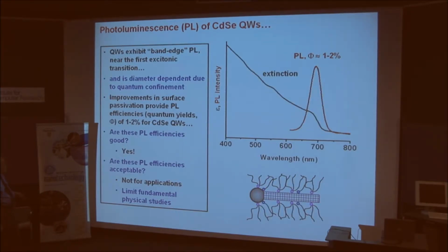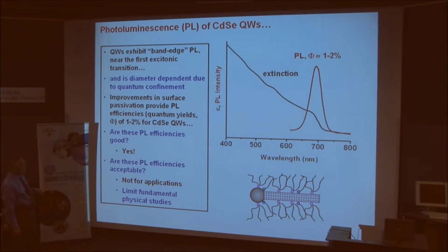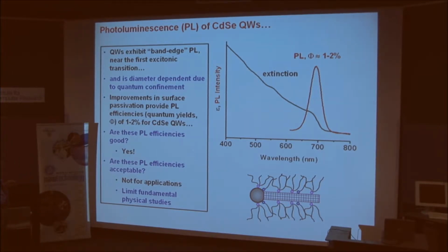Okay. Now, wires also exhibit photoluminescence, and in fact they exhibit band edge photoluminescence, which is a good thing. Here's the band edge. This is where the first excitonic transition occurs. We can excite higher lying excitons, but a higher lying exciton will always relax to the band edge before recombining radiatively. So all the photons come out here at the band edge. And that, of course, is diameter dependent, just as the first excitonic absorption feature is diameter dependent.